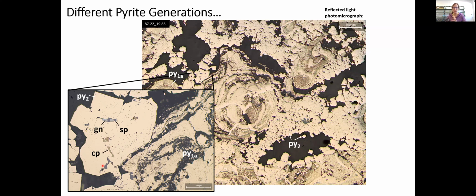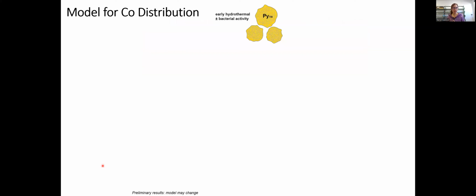in a little bit of a cartoon, so we can start putting together a model for the cobalt distribution. And we start off with our framboidal and colloform pyrite 1A, which was formed during sort of early low temperature hydrothermal activity, maybe even just diagenesis. And that probably had a lot of bugs around, a lot of microbial activity. There's not much cobalt in the system at this time, so pyrite 1A is cobalt poor.